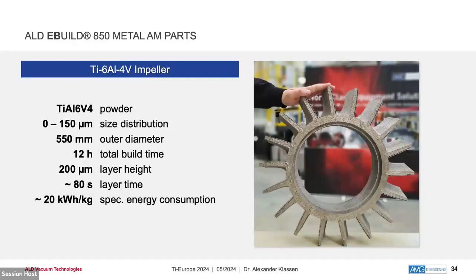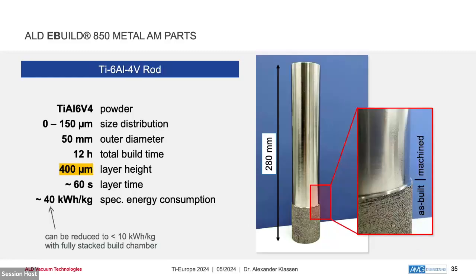of course, you can do standard additive manufacturing. In this case, it's just a demonstrator, a TI-64 impeller built within 12 hours using 200 microns layer height. Typically, layers are up to 100 microns maximum. That's why we reach such a high build rate. And to put it into extremes, we also used layer thicknesses of 400 microns. This rod has been built standing 280 millimeters in height, and it took us 12 hours to build.